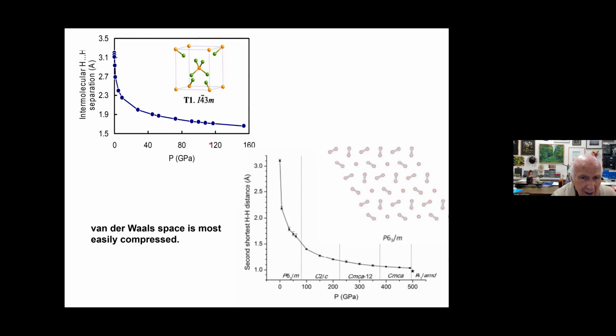And what you see here is a pressure on one scale, and on the other scale, the intermolecular H separation. And what I'm talking about is the non-bonded one between two different molecules. And what you see is it starts out in the initial structure at 3 angstroms or so. That's a van der Waals contact between two silanes, two hydrogens non-bonded. That's the minimum of the van der Waals potential. You squeeze it, and it goes down, and in the first 10 gigapascals of pressure, look how much the HH distance goes down. Not a hundredth of an angstrom, but 1 angstrom. It goes down from 3.1 to 2.1 in 10 gigapascals.